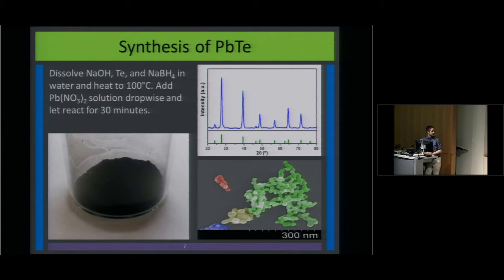So I ran X-ray diffraction on this powder just to verify that I had what I think I had. My spectrum is this blue line. If you compare that with the reference spectrum for lead telluride, which is the green lines, you can see the peaks match up pretty well. So I'm confident that I got lead telluride.